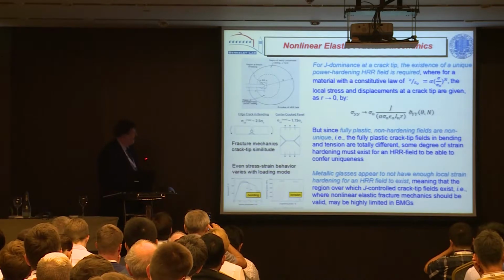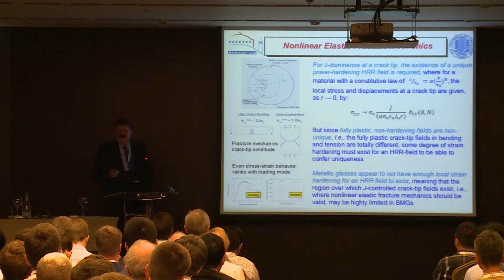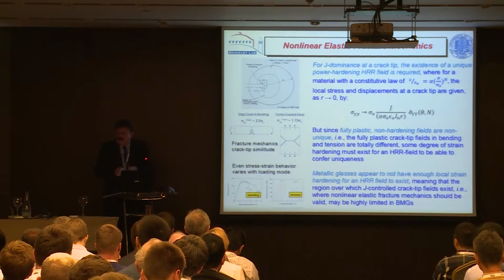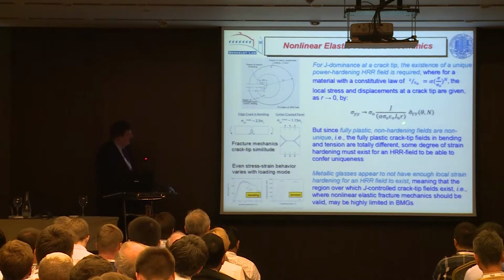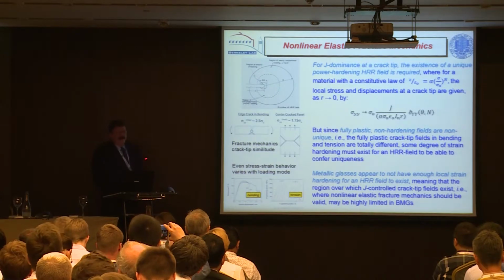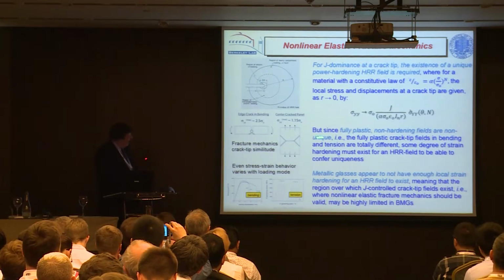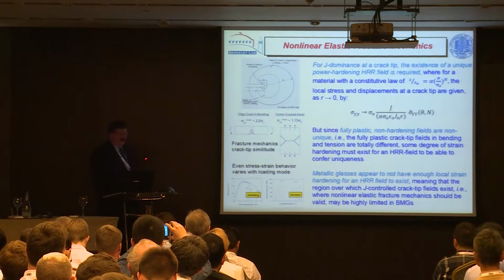The problem with metallic glasses is they don't have local hardening. In that little zone ahead of the crack tip, you don't have enough power hardening, so there probably isn't very much of an HRR field there, and the old notion of slip-line fields is a pretty accurate way of looking at this.